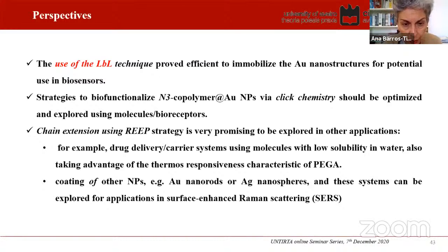Chain extension using the RAFT strategy is then shown to be a very promising approach to many other applications, namely for drug delivery, using molecules that have low solubility in water, and also this use of PEGA allows us to explore the thermal responsiveness of these nanostructures. Coating of other nanoparticles, namely gold nanorods or silver nanospheres, and so on, may allow the exploitation of these functional nanoparticles for surface enhanced Raman scattering, which can really be quite promising.